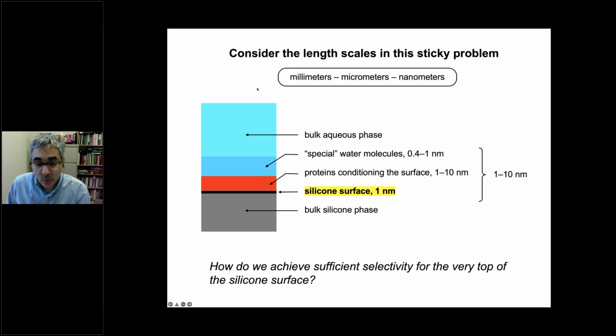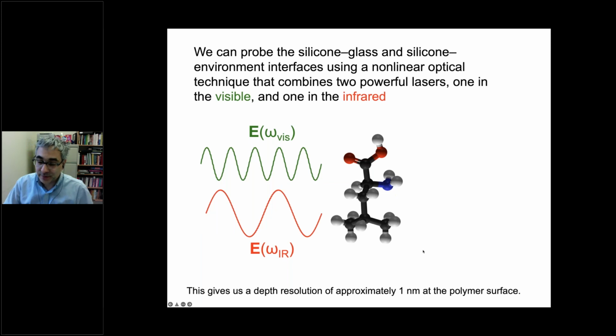And the thing is, this whole interaction distance has a length scale less than 10 nanometers. So we need a way of probing very, very fine structure like this. And it's difficult to do this with any kind of probe, let alone optical probes. But in our lab, we have one trick up our sleeves. And this is one of our specialties in the characterization, is we use a type of nonlinear optical spectroscopy.